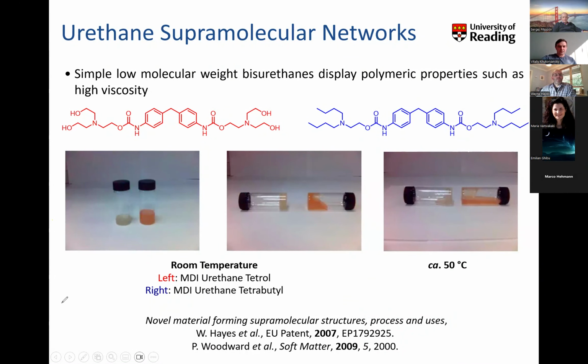So the structure in red, he managed to isolate this material. It's got a molecular weight of just over 600, but it didn't behave like a relatively small molecular weight material. It behaved very much like a polymeric gel, and that compound is in the left-hand vial, the creamy-coloured compound. And when he turned the vial on its side, with all the solvent removed, he realized that material just simply didn't flow at ambient temperature. You had to heat it above 50 degrees to get that material to flow.